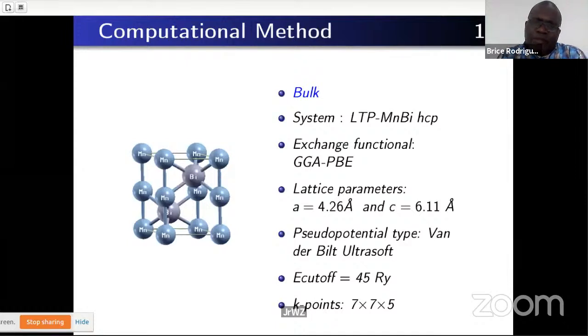The lattice parameters are a equal 4.26 angstrom and c equal 6.11 angstrom, which we obtain by minimization of the energy.